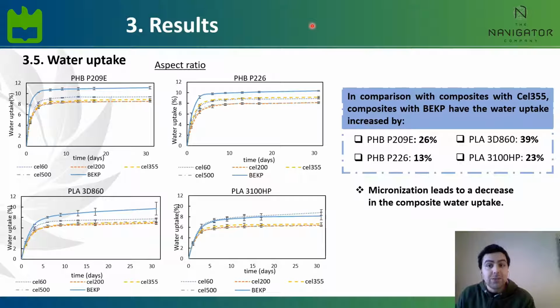When analyzing the water uptake of composites with fibers having different aspect ratios in comparison with non-treated bleach eucalyptus kraft pulp, we see that all composites with 40% bleach eucalyptus kraft pulp, here in the blue line, have a water uptake increased by 26, 13, 39, and 23% in comparison to composites having cellulose 355 as a reinforcement. And that leads us to conclude the micronization procedure yields composites with inferior water uptakes. The reason behind these results is possibly the increased wettability of the shorter fibers, which leads to a decreased porosity. In turn, the decreased porosity lowers the ability of the water to permeate inside the composite.